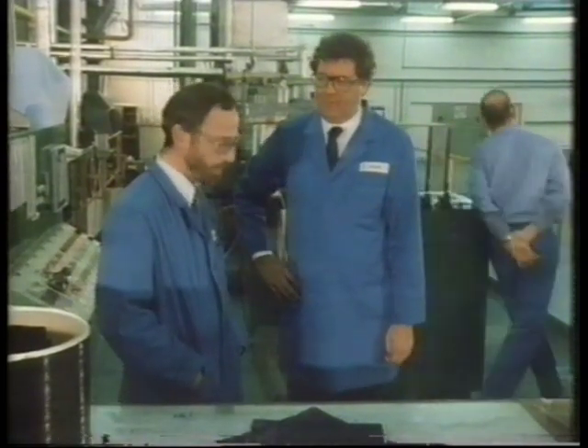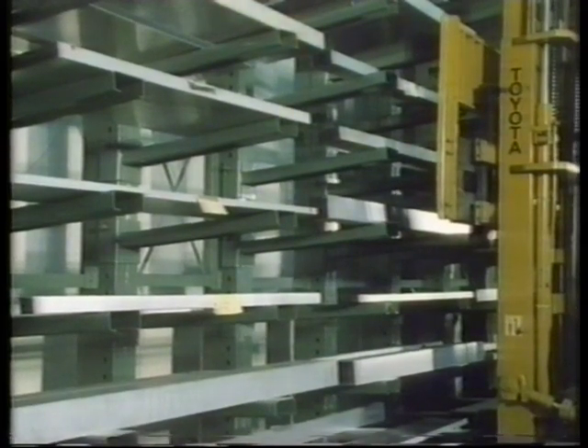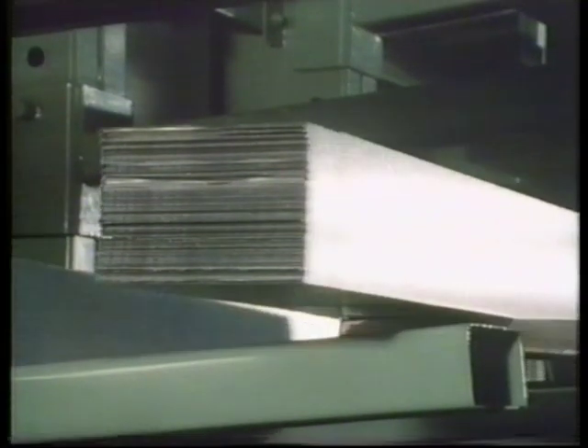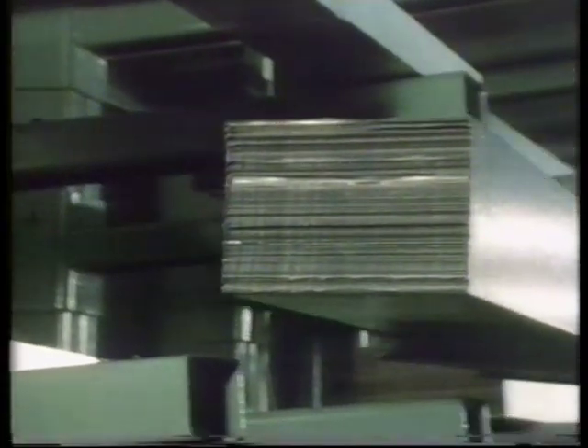And what do we need for our casing? At least 4 sheets laid at 45 degrees to each other to take stress in all directions equally. Let's see the middle part of the sandwich. The aluminium core, that's in the other workshop. They print epoxy adhesive on aluminium sheets in a striped pattern and bind the sheets together with heat and pressure. They cut slices from the HOBE block, as they call it.